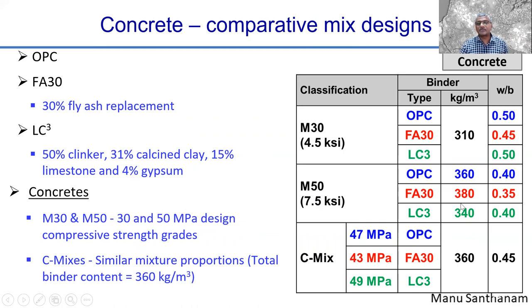So in these two cases, obviously we went for different binder contents and water binder ratios to get the particular grade of concrete. Whereas in this mix, which is called a C-mix, we had the same binder content and water binder ratio, okay? And you can see that with that, we are able to produce concretes of this 43 to 49 MPa strength. So more or less similar strength, except that LC3 is giving slightly higher strength as compared to fly ash based mixes. But not too much to emphasize on the strength. It's more the durability that we want to emphasize.